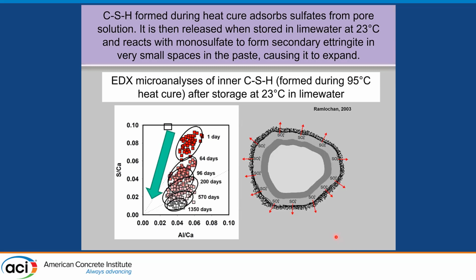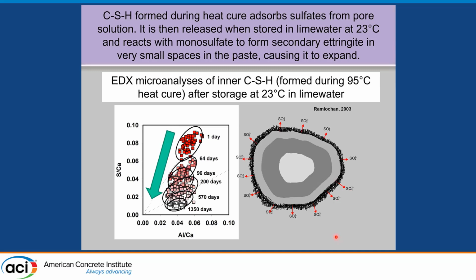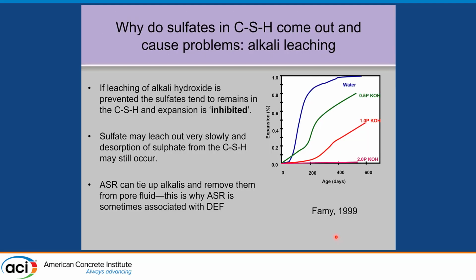So that's the CSH layer on the right-hand side. So this would be the CSH layers, and that sulfur is going out of the CSH and coming out into the surrounding matrix. And so this is just a schematic. The sulfate was in the CSH. It's then exsolving out through the system and getting removed over time. So the sulfates largely come out because of the alkali leaching.